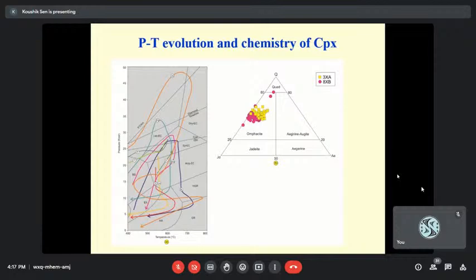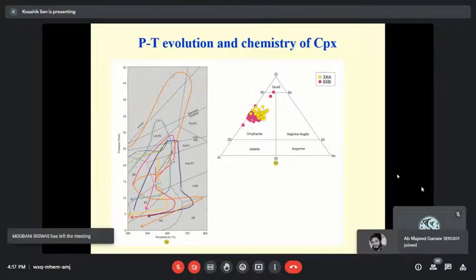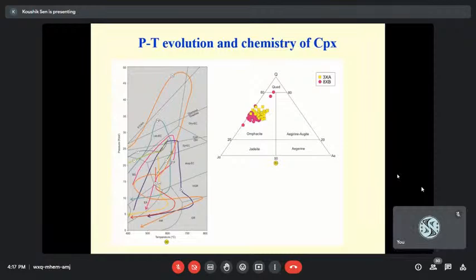Then before we carry out our lattice preferred orientation studies of different minerals, mostly omphacite, we did some chemical analysis also through EPMA. And there, sensu lato omphacite, in most cases, although there are jadeite-rich parts also, but they are very rare, and in some cases only present in the core of some clinopyroxenes. These are taken from two samples which we included in our EBSD analysis.